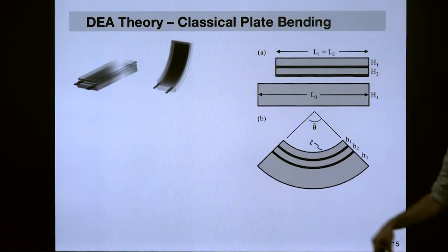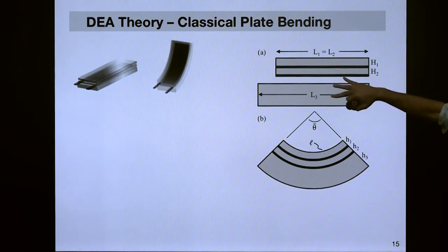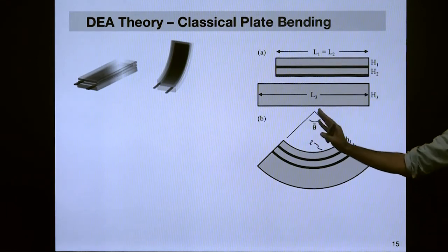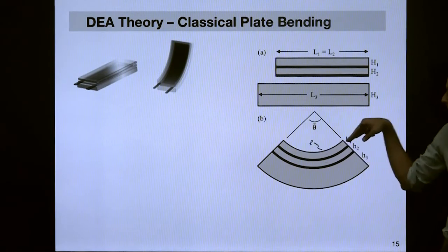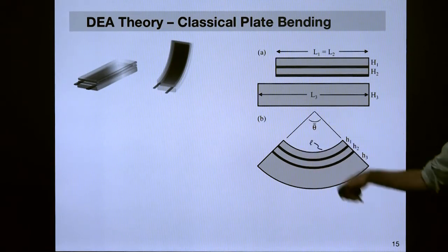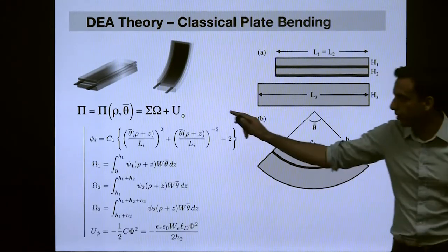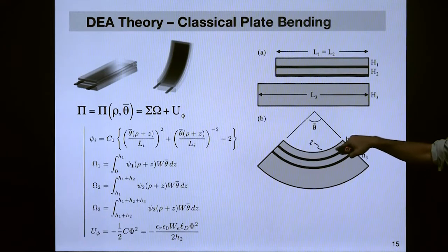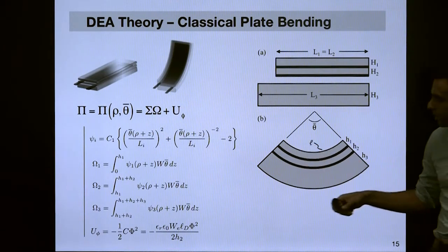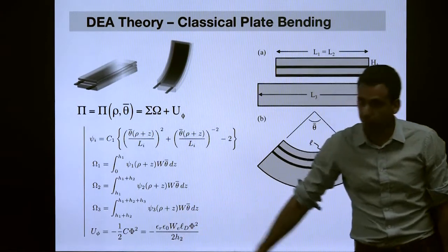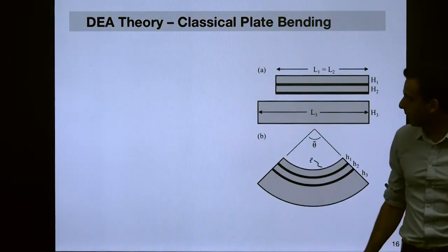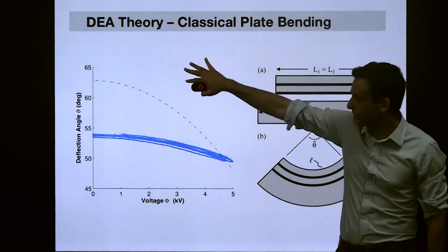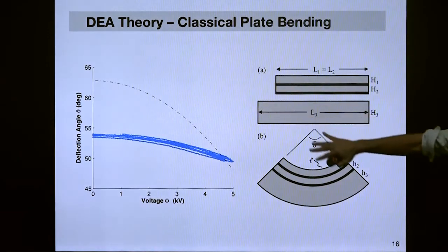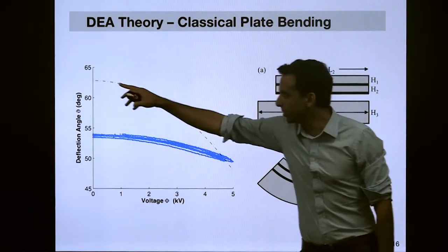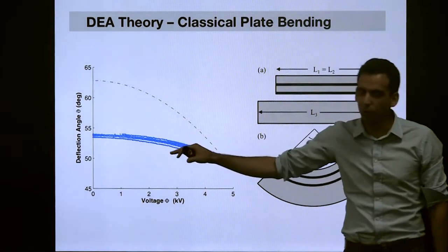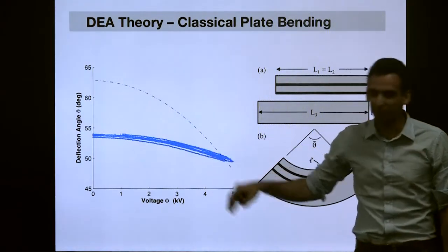And so we fabricate these, and if you just assume a planar, circular arc during bending, we can again use our Rayleigh-Ritz technique and calculate what the elastic strain energy is just due to that pure bending. We can balance that with the electrical enthalpy. We get our total expression for potential energy, minimize it with respect to bending curvature, and we get this dashed curve that is in fairly poor agreement with our experimental results.